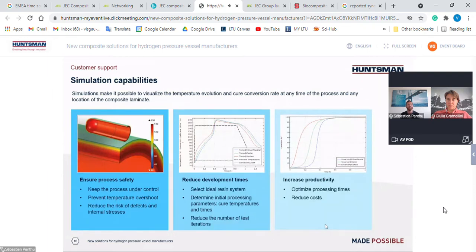And as well, to protect some of the components of the pressure vessel, like the inliner or even the sealings or the adhesives at the connection on both parts. We can also visualize the degree of cure. Thus, this will help to optimize later on the productivity. So, as you can understand now, we can already reduce development times by reducing the number of tests and reducing the number of iterations. We select the resin system first, then we determine initial processing parameters, cure temperatures and times. And then when it comes to real testing, we save a lot of time. And after this, when we keep moving forward, we make the model even more accurate, and then we can even further increase productivity, just having the right time and the right temperature in order to reduce costs and being productive.